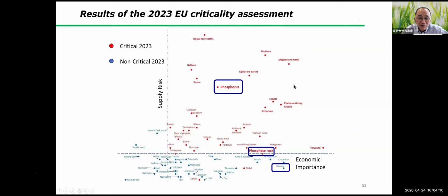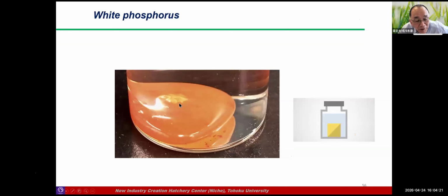This was already shown. White phosphorus is important, but under very high risk. This is white phosphorus we made. It's not white; it looks yellow, but the surface was slightly oxidized, so the color becomes yellow. This is a very dangerous material. If you put it in the air, it easily ignites and starts to burn. So usually it is kept in water.